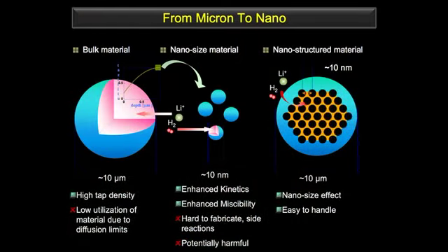And this is just a cartoon that illustrates the advantage of going from a bulk material where you have a lot of mass transport limitations to a nano-sized material where, of course, the path length for transport is far diminished. And one can also then imagine going to nanostructured materials where they convey all of the benefits of nanoparticles, but in a system that is somewhat larger and spans microns. So in this case, the materials will have a high tap density, which refers to the actual density that you can get in the electrode, but there can be low utilization due to these diffusion limits because of mass transport. Here we have enhanced kinetics. These materials can be hard to fabricate. In this case, as I said, they convey the advantages of a nano size, whereas they're much easier to handle.